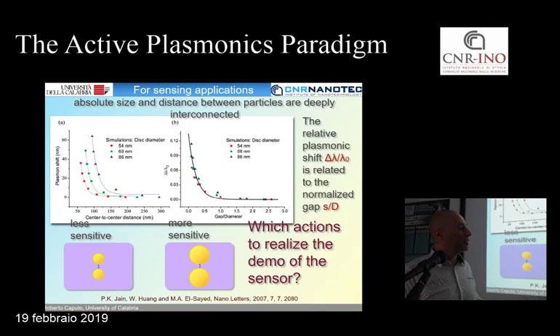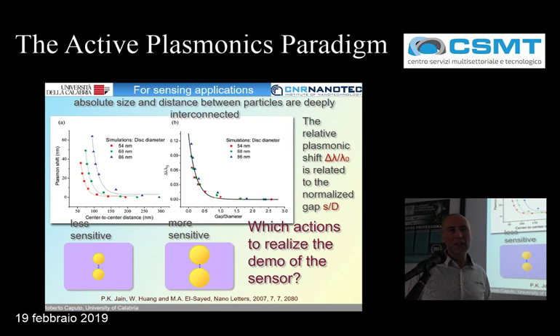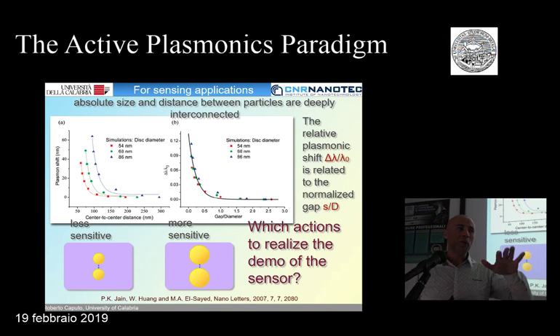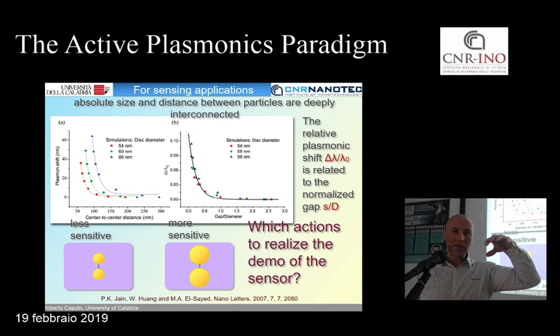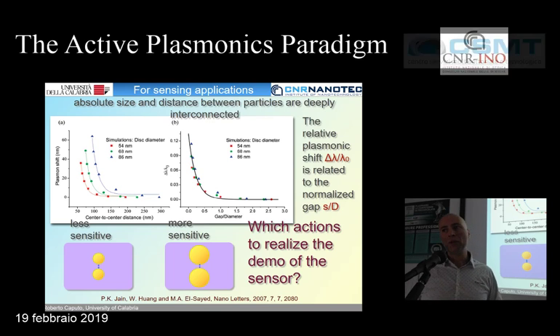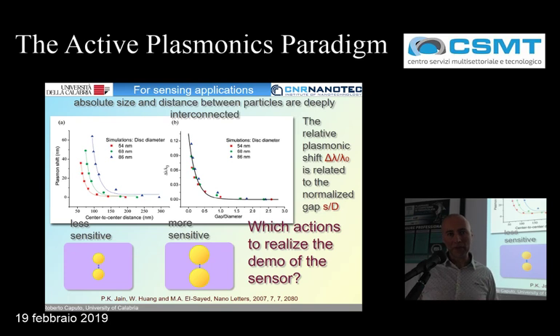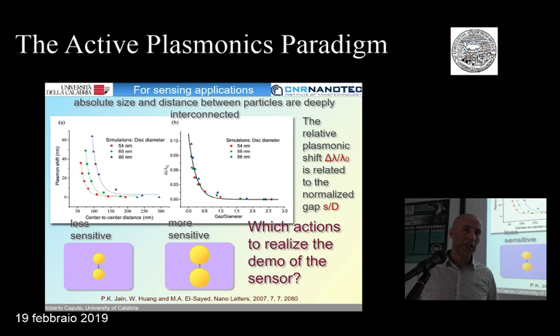Indeed, what I said is that they consider just the particles without substrate. And in practice, we don't know how much the particles are embedded in the substrate. So we suppose they are half embedded, half outside. To simulate the real case, you should at least estimate this. So to avoid many problems at the beginning, we just consider the particles themselves without substrate, and the results are affected by this.